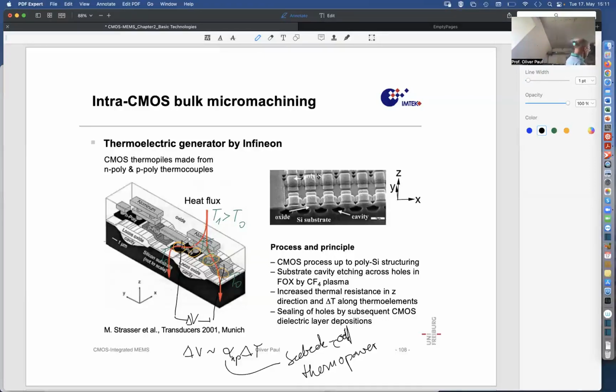But because there is n poly combined with p poly, you have an electric field caused by a gradient, and then an electric field in the same direction in the other material by the opposite gradient, because the alpha is opposite, and that adds up to a final delta V that is different from zero if delta T is different from zero.